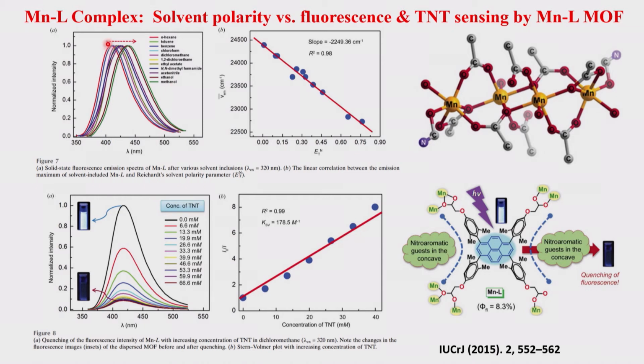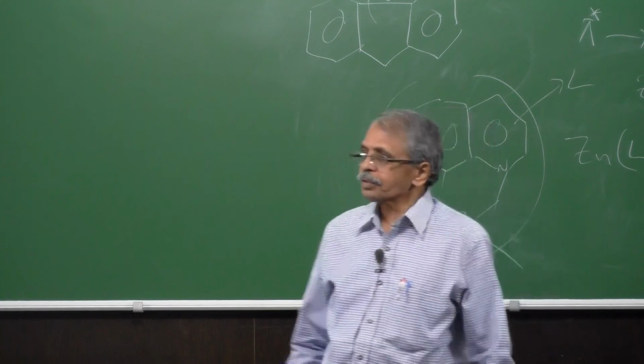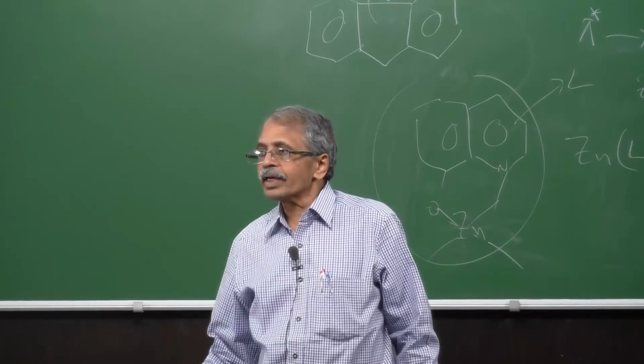You can see from here that there is a huge amount of emission wavelength shift, going from somewhere around 400 to close to 450. If you look at it in terms of wave numbers, it will go from 22,500 to 24,500, which is around 2,000 inverse centimeter variation. Now if I take the polarity of each of these solvents and put it on the x-axis, and take the emission in terms of nu bar, I can make a kind of straight line between these systems. You can see that very well, so it is very well correlated to the polarity.